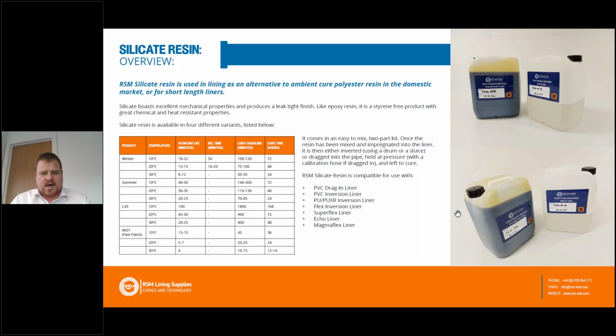Silicate resin has absolutely fantastic chemical resistance to a range of different acids and alkalis, and also, as an ambient cure product, the best temperature resistance. In terms of pure water, between 90 and 100 degrees resistance using silicate resin.